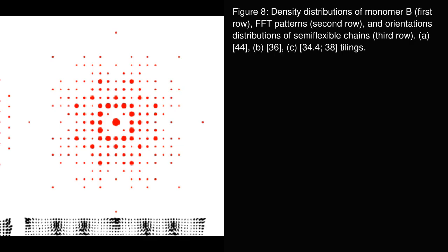For example, 4^4 tiling is interpreted as repeating square polygons cyclically touching at vertices, marked by monomer B at higher concentrations, forming these vertices. The authors reproduced the previously reported 4^4 and 3^6 patterns, while also discovering a more complex new morphology, denoted as 3^4.4^3.3.4^2. Detailed model parameters for these calculations are given in Table 8.